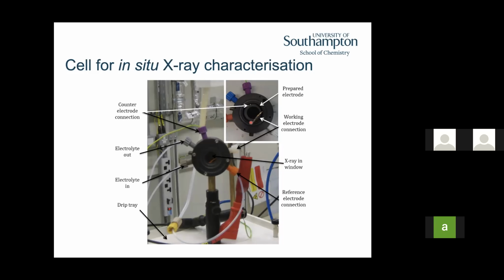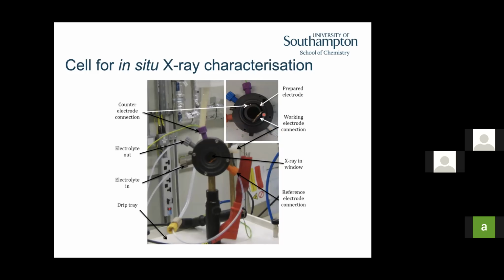So this is the underside of the cell. The counter electrode is sitting back here behind the cell. So they're concentric, but with the counter electrode a little bit displaced. And the solution will then flow through here. We sometimes put filter papers across the working electrode to ensure wicking of the electrolyte across the electrode. It really depends upon the hydrophilicity of the ink that we've made.